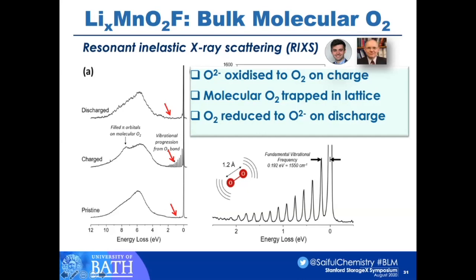We find from RIXS, from resonant inelastic X-ray scattering, evidence of molecular oxygen in the bulk. On the left are the spectra starting from the pristine, going to charged, and then going to discharged. So it is reversible. The O2 minus is being oxidized to O2 on charge. That molecular O2 is trapped in the lattice, and then the O2 is reduced on discharge. This is under ultra high vacuum conditions, and we've done it at different temperatures, so there is no evidence of beam damage either. So that's the take home message for this oxyfluoride.